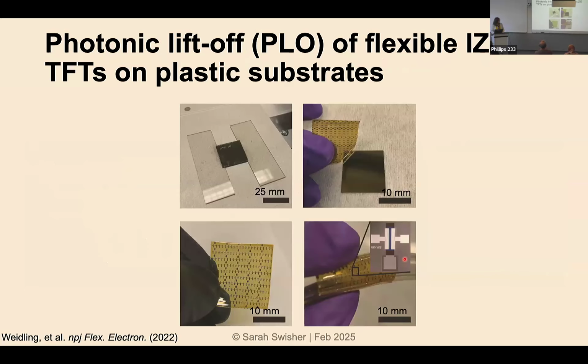So the process for this liftoff looks like this. This is the device flipped upside down. And we just suspend it on these two glass plates. This goes into the processing tray, and it's illuminated from the back. And then right after the pulses, this peels off really nicely. There's not a lot of sticking force. We were able to tune the parameters of this pulse, the pulse light, so that it comes off without a lot of residual stress in the film, so it's not rolling up on itself. And we get these nice flexible IGZO transistors.